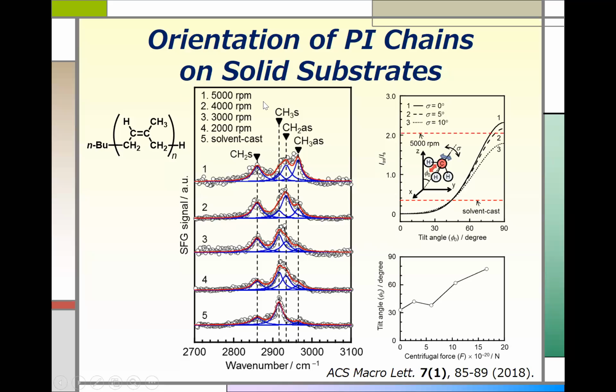Again, we have applied some sum frequency generation spectroscopy to take a look at the conformation of polyisoprene on such substrate. So again, we have applied two different techniques. One of them is the solvent casting method, and another is the spin coating method with different spinning rates from 2000 up to 5000 RPM. And here's what we got by SFG.